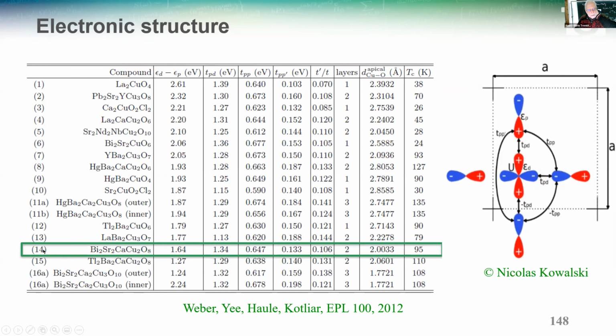Just for reference, we'll take this compound that I will call the covalent model, because epsilon P minus epsilon D is now small. You see it's 1.64 electron volts, compared with the large number we had before. The large number we had before was measured in units of TPP, which is of the order of 0.6 electron volt. What's remarkable about TPP is that it doesn't change very much from one compound to the other. So we use this as our unit of energy: TPP is 1, and everything is measured in units of TPP.